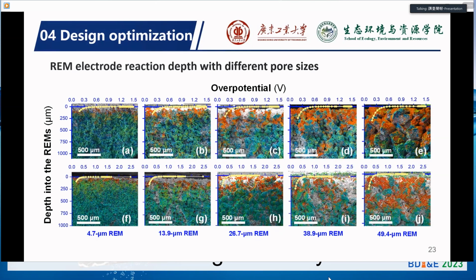When we increase the hole size, the mass transfer is a bit slower as compared to small size REM, but they have a larger reaction depth. So we may conclude that people should think about either the reaction depth, but also the mass transfer inside the REM. So these two parameters are significant factors that have a trade-off effect.